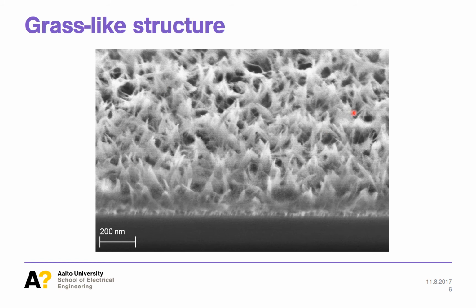We attribute the creation of such specific topography in part to the effect of water surface tension. When the water dries off the samples, it brings the dismantled film pieces together, like here, creating close to conical structures, though very chaotic. The transformation increases the film thickness, as you can see in the SEM image. The porous film is about 200 nanometers thick, while we have deposited only 28 nanometers of ALD alumina.